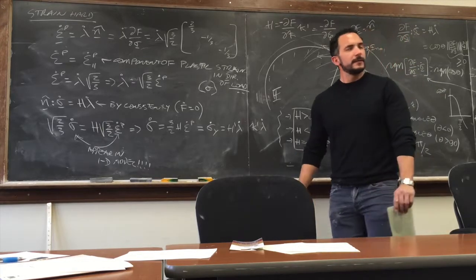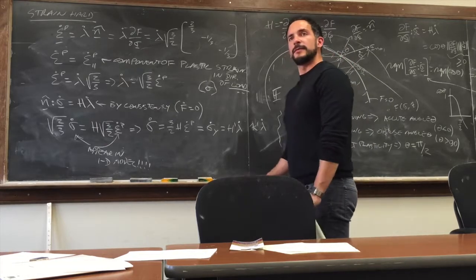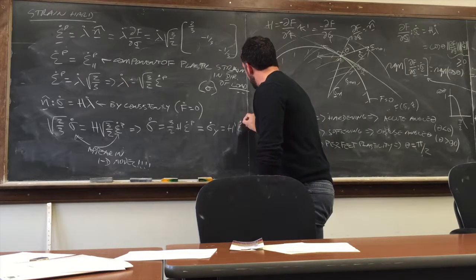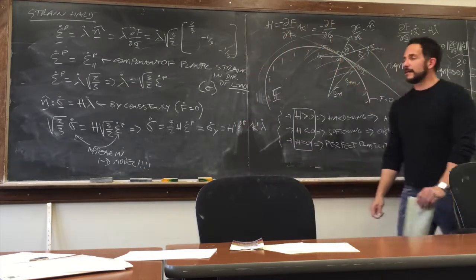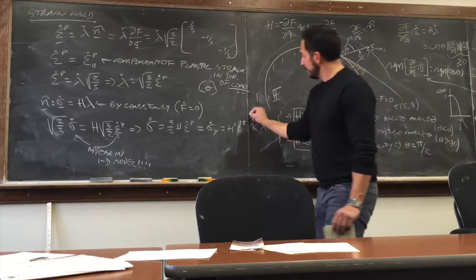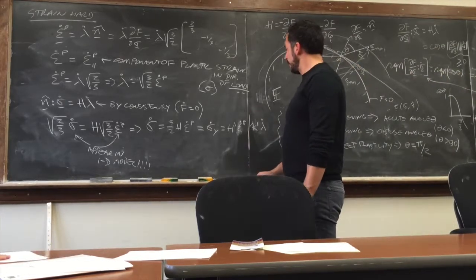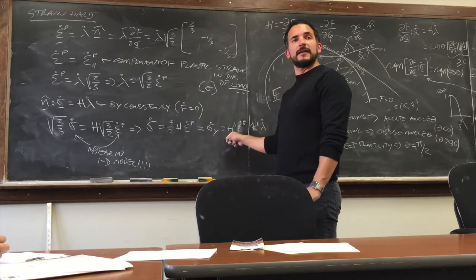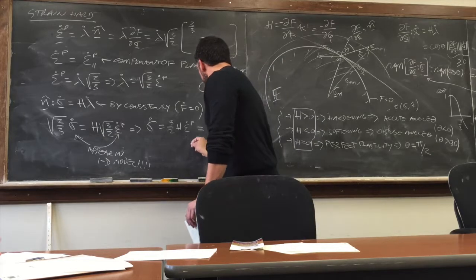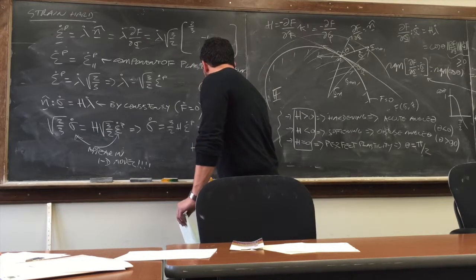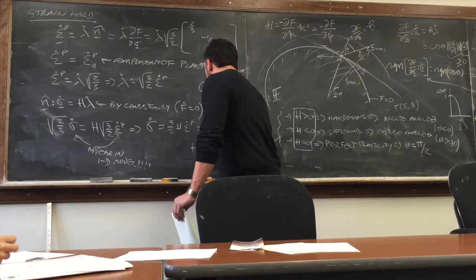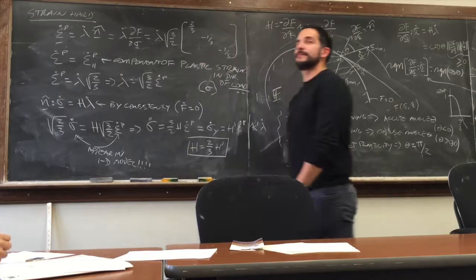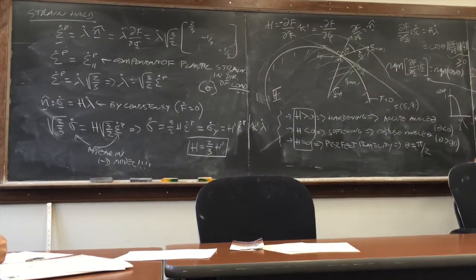Kind of? Yeah? Is that still in 1D? Well, in 1D we called it like this, so let's be consistent. Okay? For the isotropic hardening model. So this gives us a relationship between the hardening moduli. This is your plastic modulus. So in 1D, so in 3D, H equals 2/3 of H prime. Okay?